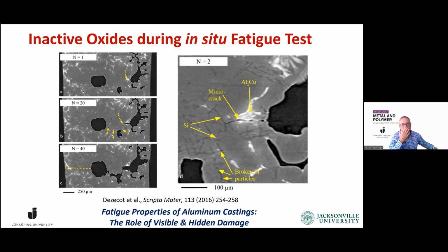So if you don't see this in real time, and you look at the fatigue specimen, you say, oh, okay, this is fatigue damage. But actually, the fatigue crack is following the transfer damage, the liquid metal damage that was created during processing. So that is the main thing. What has usually been referred to as fatigue damage is in fact damage given during the processing of the liquid.